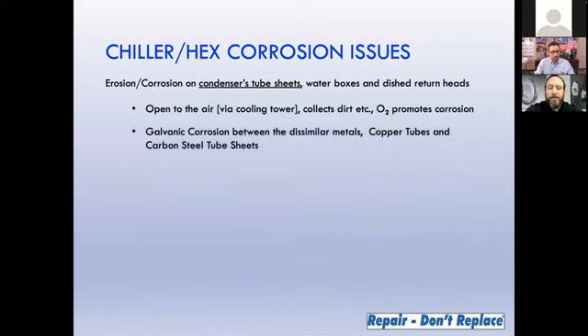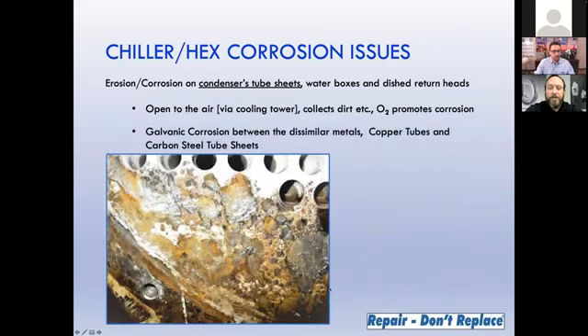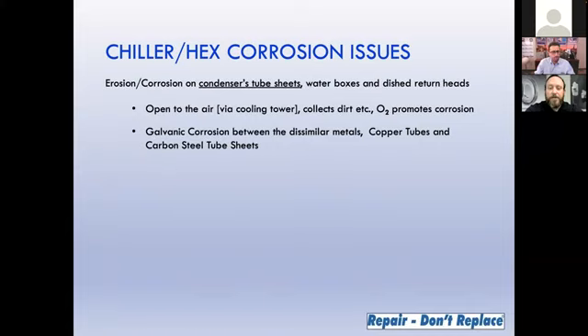Another type of corrosion that we often run into is galvanic corrosion, which is corrosion between the dissimilar metals of the copper tubes and the carbon steel tube sheet. As you can see in this photo, the corrosion is starting to form all over the tube sheet, but really paying special attention in between the tubes where bimetallic corrosion is the most severe. Occasionally, the evaporator bundle is also treated, but they are usually on a closed loop system and much less prone to corrosion.